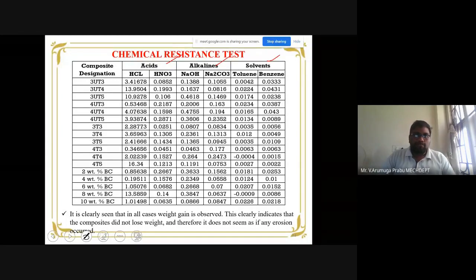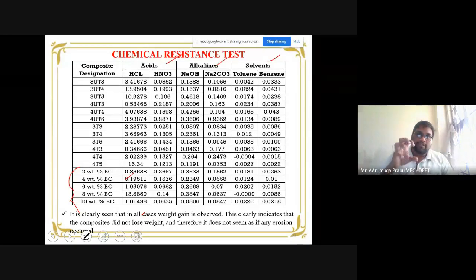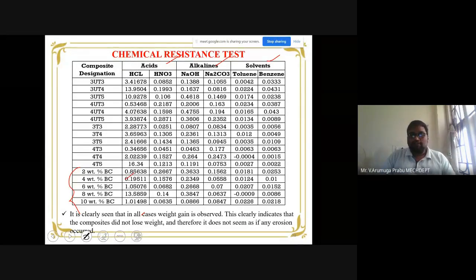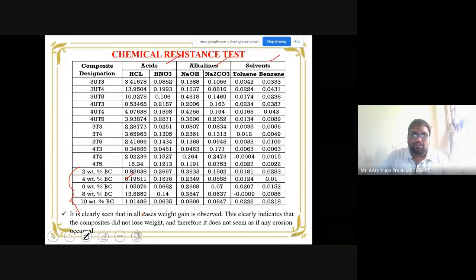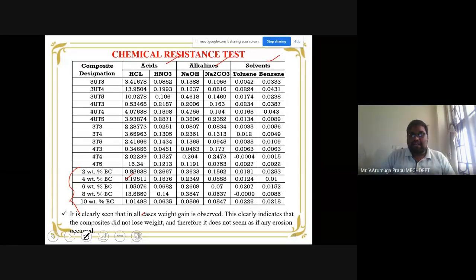And interestingly, what we note is that the biochar based composites show a weight gain in all the cases. That is, it has the capability to absorb the chemical. So a weight gain is noted in all the cases, which clearly indicates that the composite is not going to lose any weight, like the situation in our erosion studies. So same as in our erosion studies, here the composite does not lose any weight, which shows an interesting phenomenon.